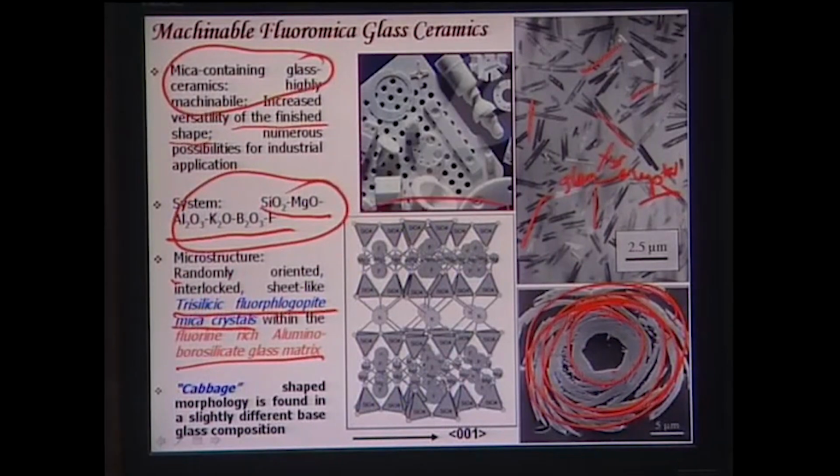This is the characteristic structure of these crystals. In this structure, the potassium is located at the central region of the lattice, and then you have the SiO4 silicate tetrahedron, and your fluorine and magnesium are located in between the silicate tetrahedra.